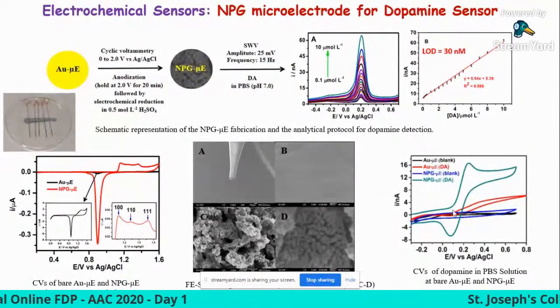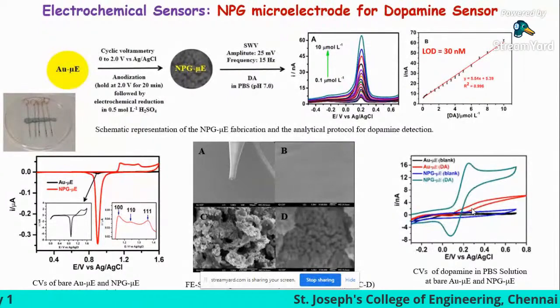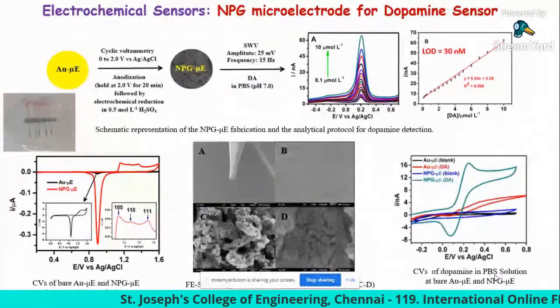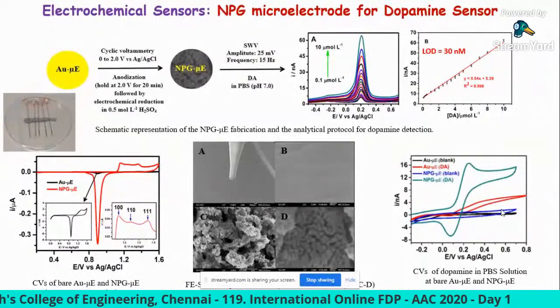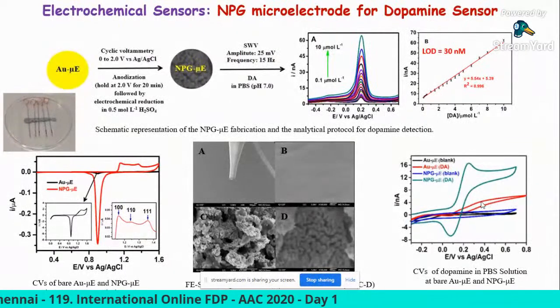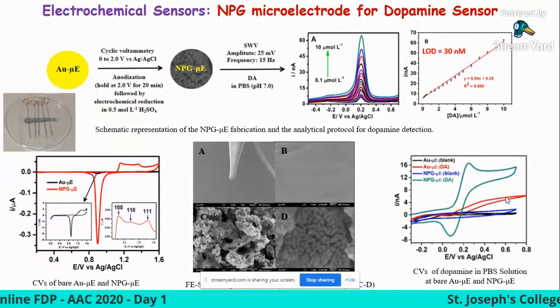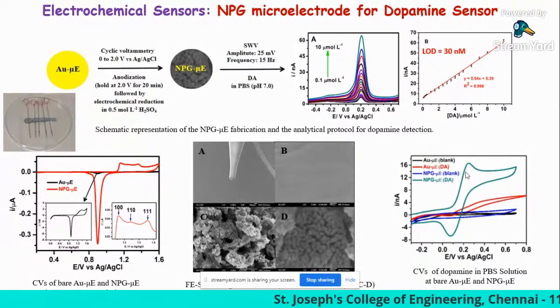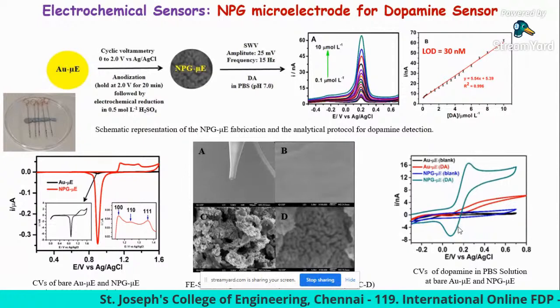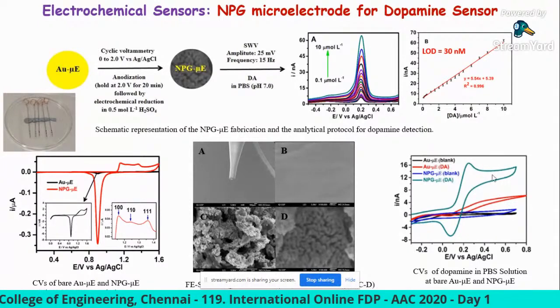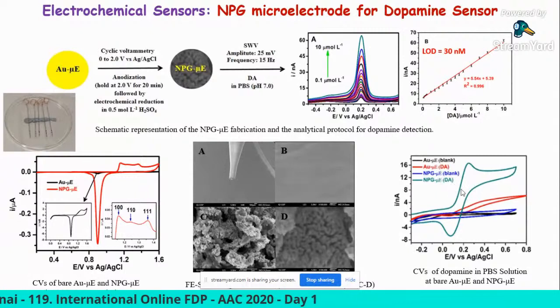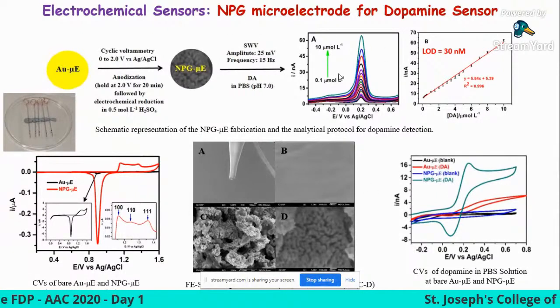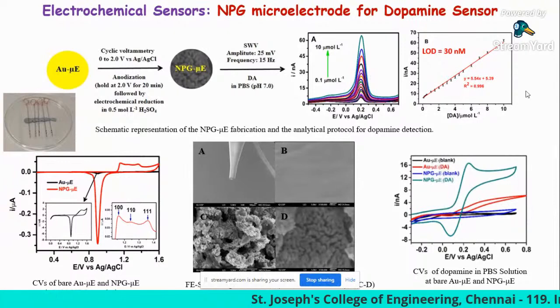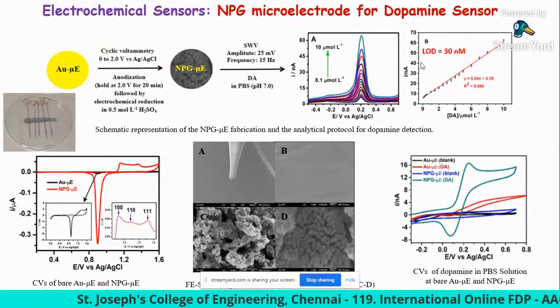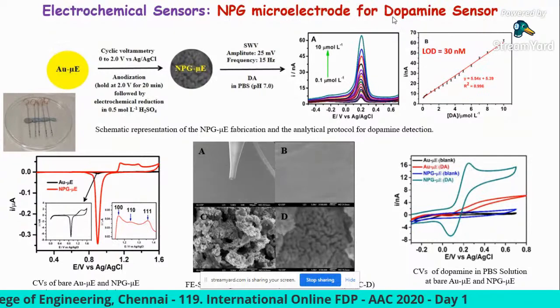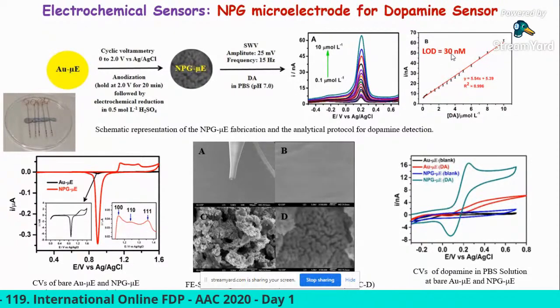These are the cyclic voltammetric responses of dopamine oxidation recorded in phosphate buffer solution, where you can see there is a clear change. The red line is the bare electrode, and this is the nanoporous electrode. There is a clear shift in the oxidation potential as well as an increased current signal, which indicates the excellent electrocatalytic activity of nanoporous gold for dopamine sensing. And this is the square wave voltammetric response to record the calibration curve. From this, the developed sensor shows a minimum detection limit of 30 nanomolar.